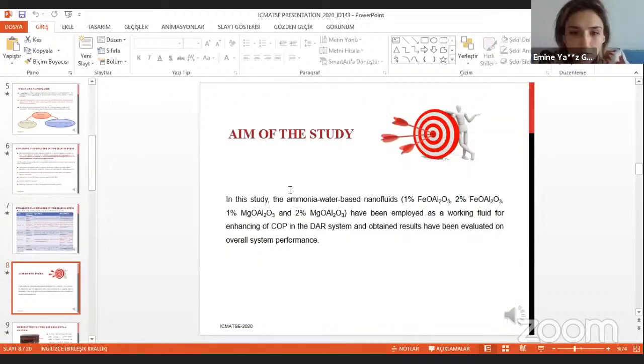The aim of this study: we use ammonia water-based nanofluids with iron oxide alumina spinel at 1% and 2%, and also magnesium oxide alumina spinel at 1% and 2%, and we compare them in an experimental system, and we obtain some results.